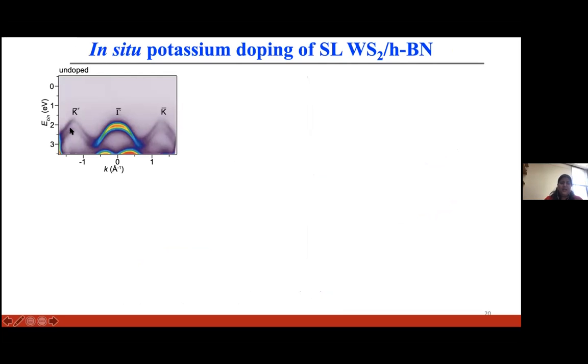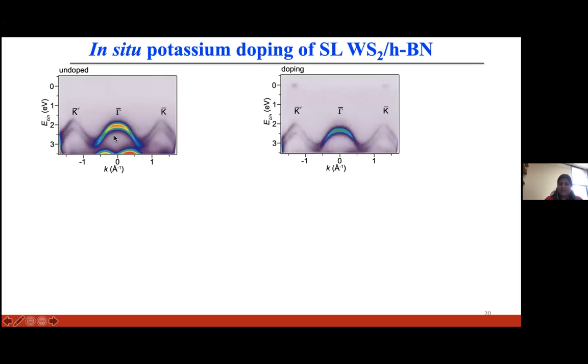Here's the dispersion along the K'-gamma-K direction for the undoped sample. And here on the right, I'm showing what happens when we dope it with potassium. You can see the conduction band appears. If you look carefully, you will see that as we dope more, something is happening at the K point, and not much is changing at the gamma.